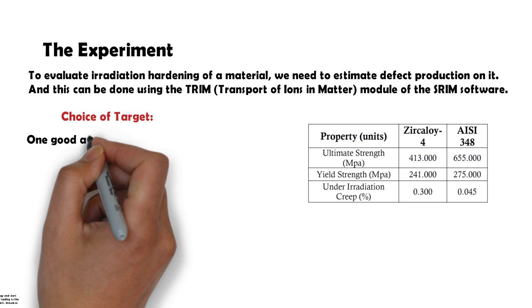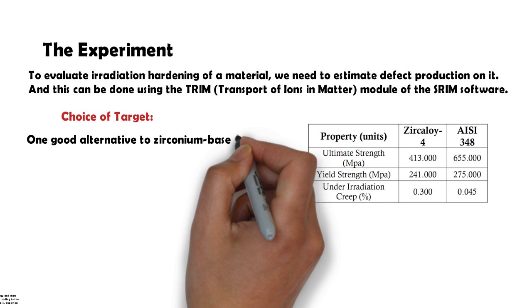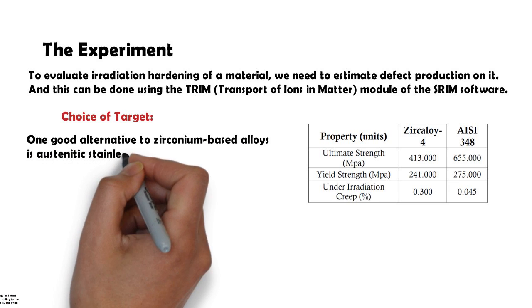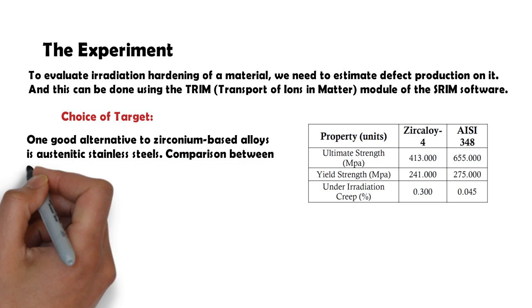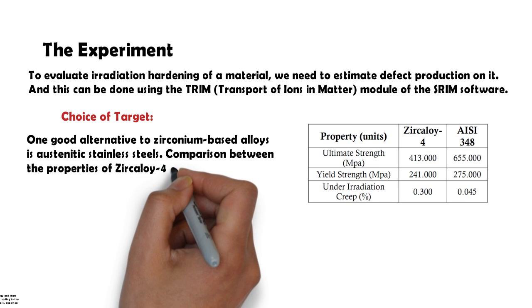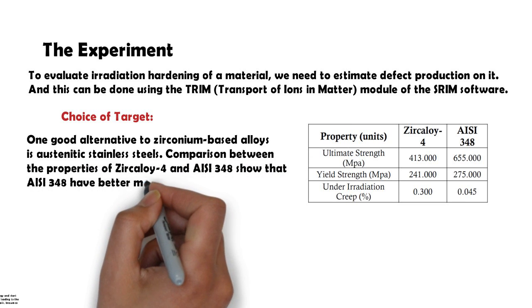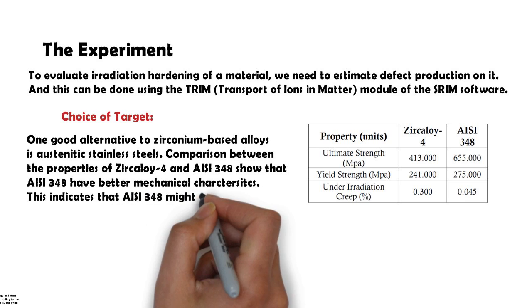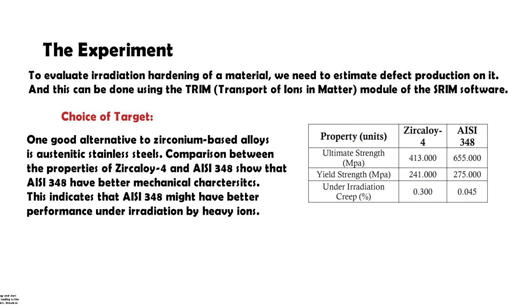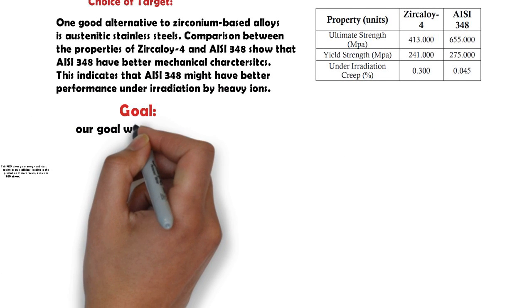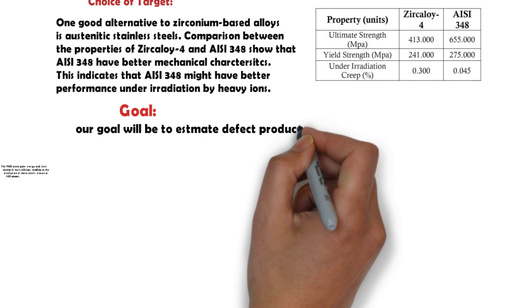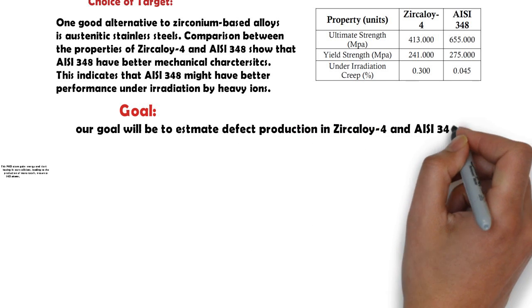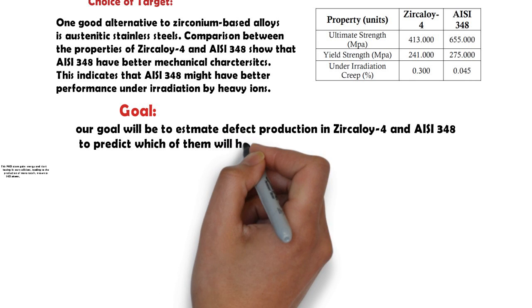One good alternative to zirconium-based alloys is the austenitic stainless steels. Comparison between the properties of zirconium and stainless steel shows that stainless steel has better mechanical characteristics. This indicates that stainless steel might have better performance under irradiation by heavy ions. Our goal will be to estimate defect production in zircaloy 4 and austenitic stainless steel 348 to predict which of them will have less radiation hardening.